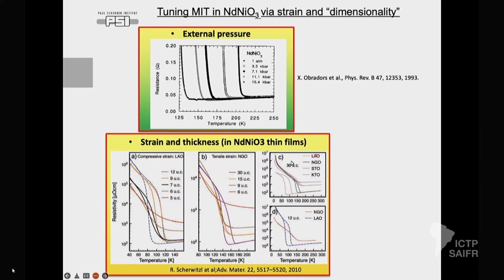So here is a summary of all of what I said now. If you have 30 unit cell, it should be bulk-like. With a different substrate, you could see that there is a way to tune the metal insulator transition from roughly 70 Kelvin up to almost 200 Kelvin. So 130 Kelvin is the range of tuning the metal insulator transition.